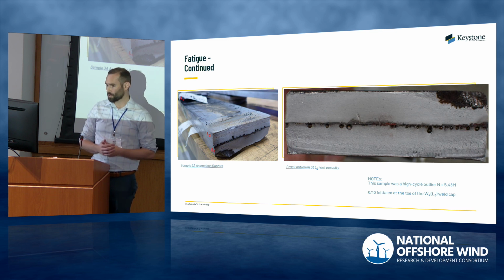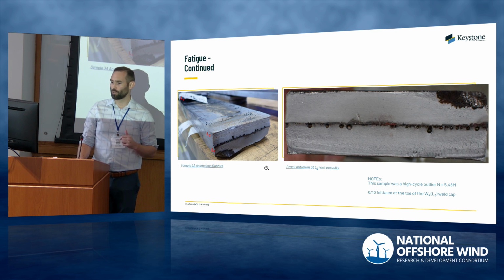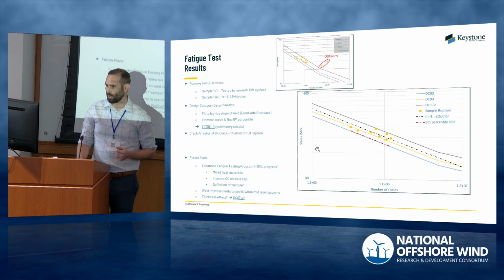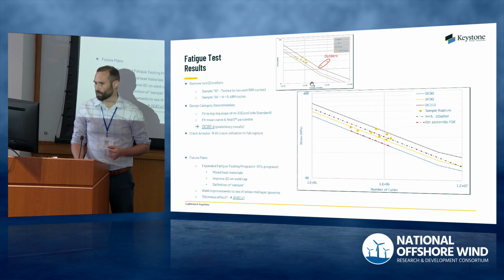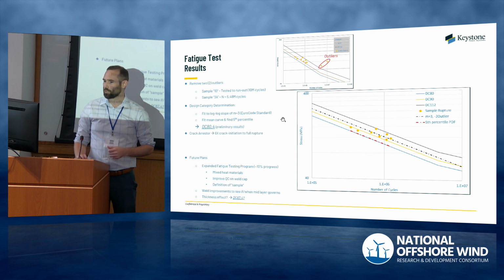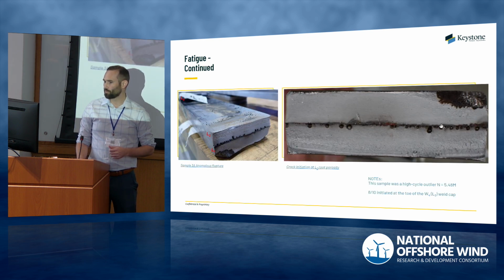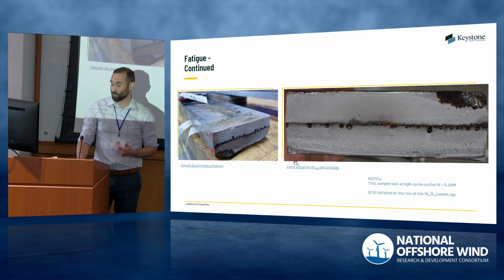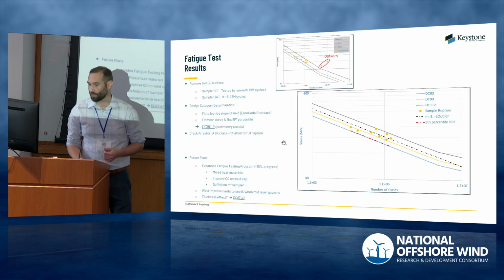Some other test samples, this was one that was kind of an anomaly. It actually ruptured in the middle layer first. We had some porosity, as you can see, but it's worth noting this was strangely an outlier on the high side. So even though we had this gross amount of porosity in this middle layer, it was an outlier on the high side of cycle count.